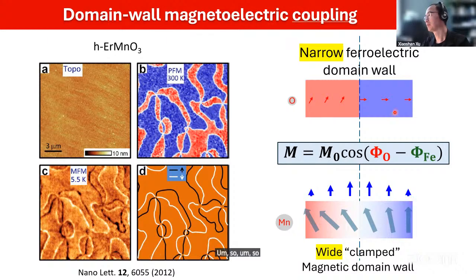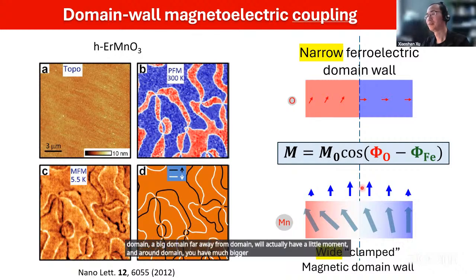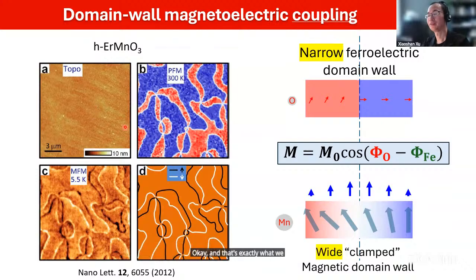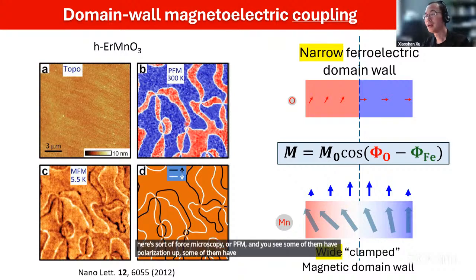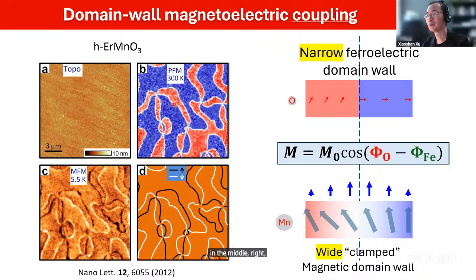So in the domain, in the big domain far away from the domain wall, we'll actually have a little moment, and around the domain wall you have a much bigger moment. And that's exactly what we see here in the experiment, right? This is a sample, or the film, with basically the height. You don't see anything. But if you use something called piezo force microscopy, or PFM, you see some of them have polarization up, some of them have polarization down, and these in the middle are what we call domain walls.